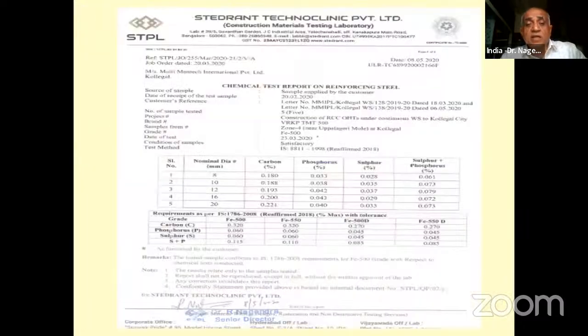So similarly, you have the opposite side, very high strength, but very less ductility. So UTS is 665, elongation is only 11.3%, which is very less. Type of fracture is a brittle fracture. First one was a ductile fracture, and this is a brittle fracture.